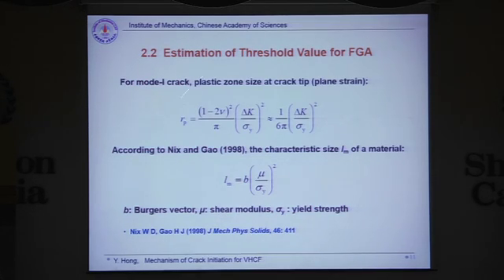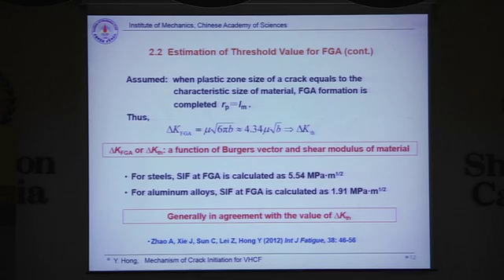We just take advantage of two formulas, of plastic zone size and of the characteristic size of the material. We assume that the plastic zone size of the crack equals the characteristic size of the material when the formation of this crack initiation zone is completed. Under this simple assumption, we come up with a result showing that the value of delta K for FGA is just a function of the shear modulus and the Burgers vector of the material.